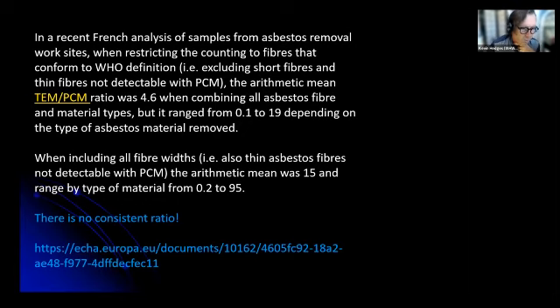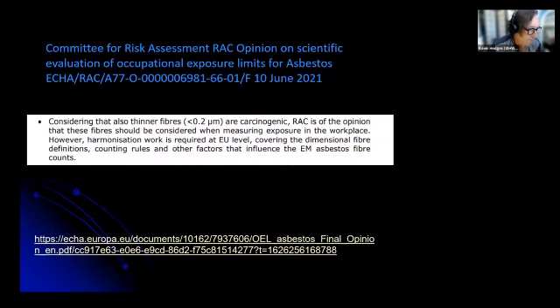So when combining all asbestos fibers and material types, it ranged from 0.1 to 19, depending on the type of asbestos material removed. When including all fiber widths, also thin asbestos fibers not detected with PCM, the arithmetic mean was 15 and ranged by type of material from 0.2 to 95. So I guess the bottom line is there's no consistent ratio between TEM and PCM.